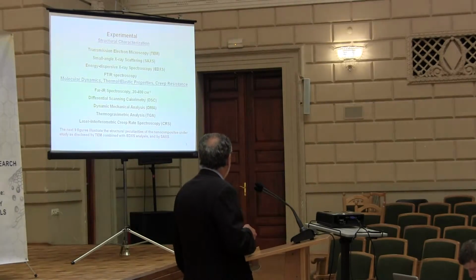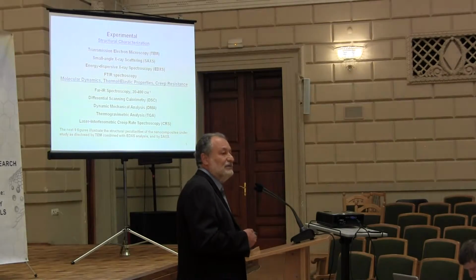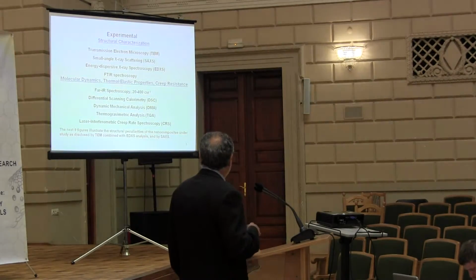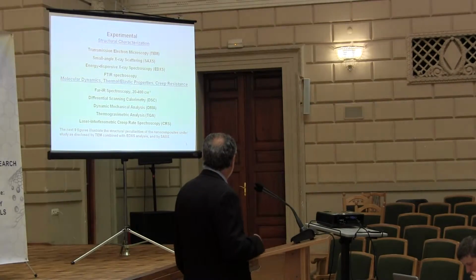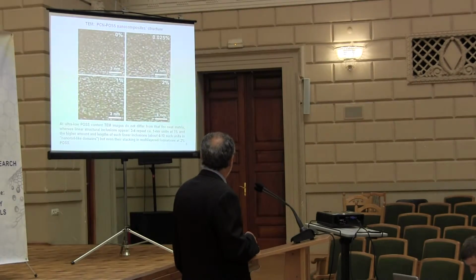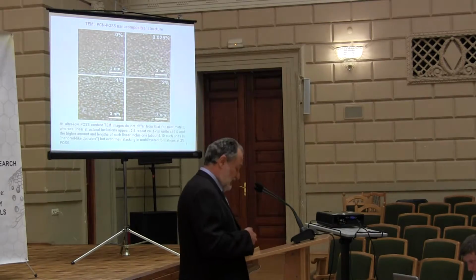Here we can see the methods we used to characterize and obtain nanocomposites. It's TEM, SAXS, EDS, FTIR spectroscopy, also far-infrared spectroscopy. The DMA is a traditional method for characterization of polymer materials, and quite specific laser interferometry and creep rate spectroscopy. So the next slides will show the results. So here we have TEM photos of the PCN-POSS nanocomposite structure.